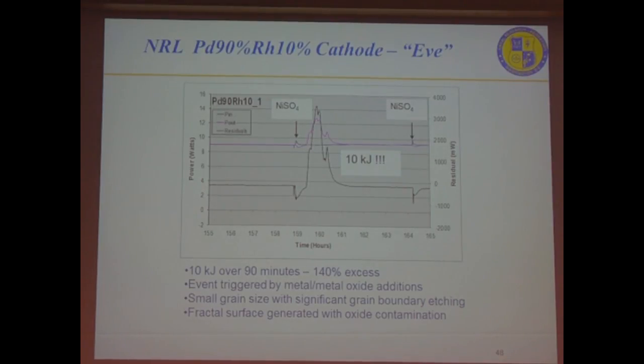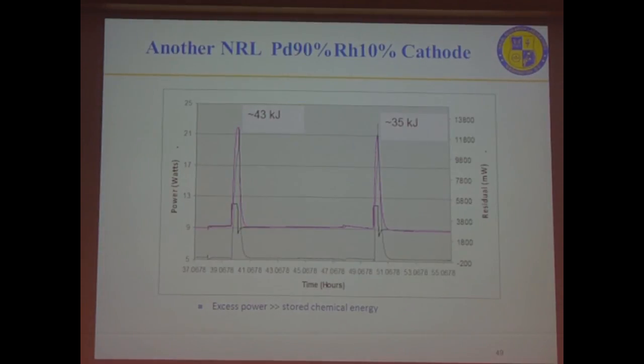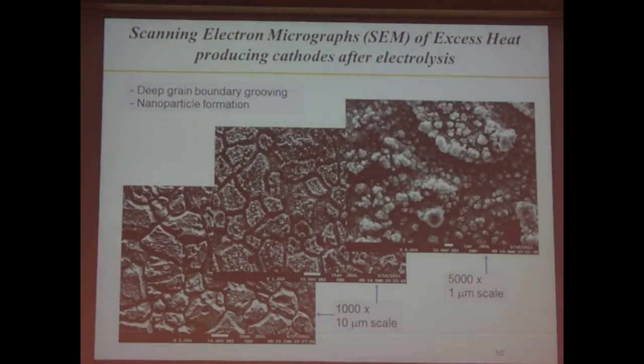Now you can say, well, it's chemical because they had some stuff which was reacting with the electrolyte, but no, the amount of heat is much, much greater than any known chemical reaction. As you can see, they got 10 kilojoules for 90 minutes at 140% power gain. This is another experiment, and this is how the surface looks. Again, with deep grooves around the grains, and these are the precipitation of the material, which is making it again a very developed labyrinth type surface, which increases the probability for excess heat.